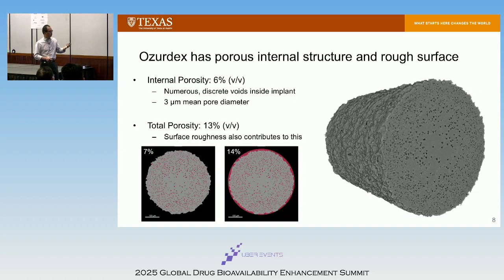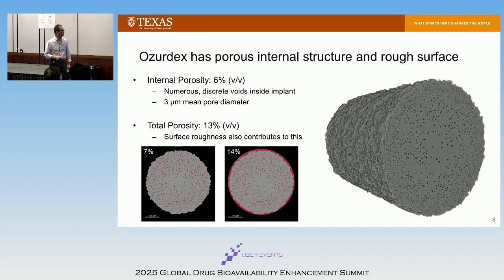So here's dexamethasone. This is a micro CT scan. And if you look at the surface, it is very rough. It also has lots of pores in there. Right? We introduced this concept, internal porosity and the total porosity. There are many ways to look at roughness on the surface.